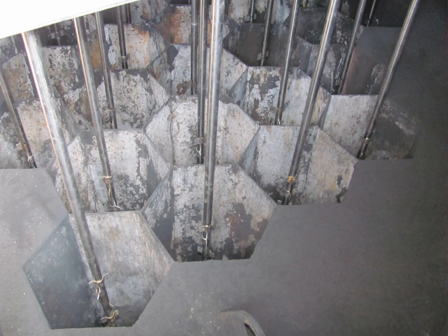In high-resistance dust layers, the dust is not sufficiently conductive, so electrical charges have difficulty moving through the dust layer. Consequently, electrical charges accumulate on and beneath the dust layer surface, creating a strong electric field. Voltages can be greater than 10,000 volts. Dust particles with high resistance are held too strongly to the plate, making them difficult to remove and causing rapping problems.